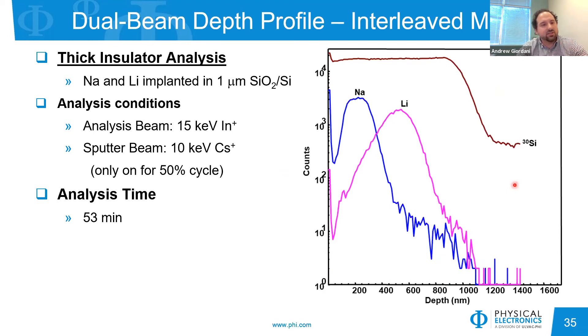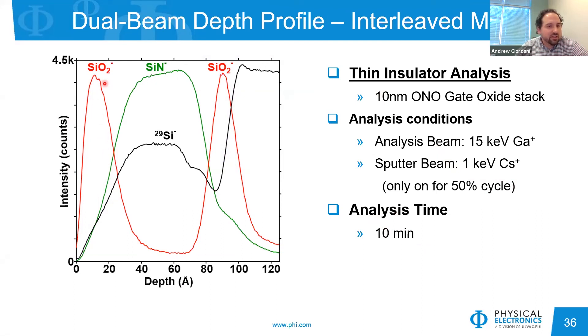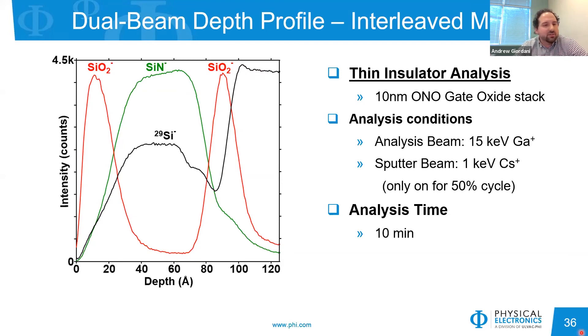Interleave mode also works well for thin insulating samples with very high data point density. A 10 nanometer oxide-nitride-oxide gate oxide stack is profiled using 15 keV gallium for the analysis beam and 1 keV for the sputter beam, providing much higher depth resolution. The analysis took only 10 minutes. Sputtering down through the sample reveals the surface oxide at roughly 2 nanometers, the silicon nitride signal increasing then decreasing, and finally the last oxide before the substrate. Operating at low impact energy gives high depth resolution and ensures no interfaces are missed due to the high data point density.